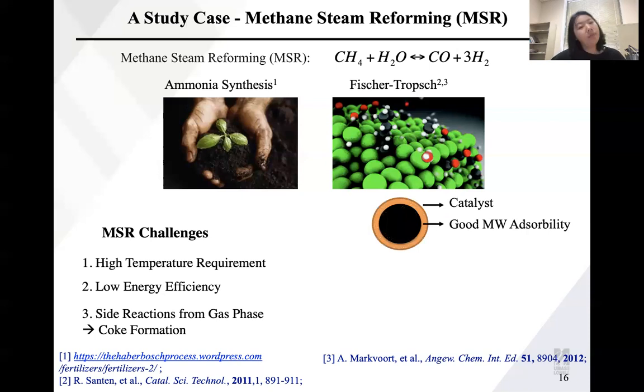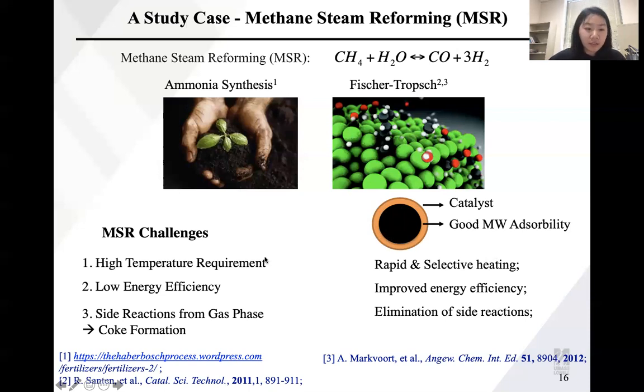We want to use microwave technology to enhance this methane steam reforming reaction. So we have our catalyst with a core and a shell. The core will be a material with good microwave absorbability. Then it will heat rapidly and selectively in the microwave, so that it will solve the challenge of the high temperature requirements of methane steam reforming, as well as improve the energy efficiency, because it heats rapidly and preferentially those materials you want to heat up. And it won't heat the gas phase, so your gas phase will stay cold, and you will eliminate the side reactions in the gas phase. Then that will solve the methane steam reforming challenges, which are listed here.